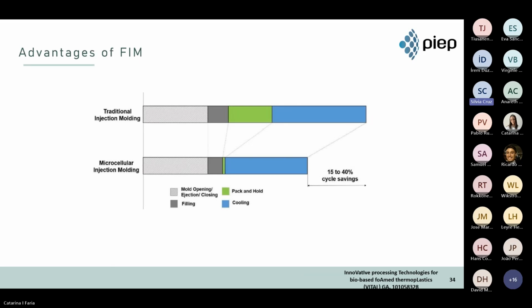So why use foam injection molding? The advantage of this technology compared to the conventional injection molding is, to start, the cycle time reduction. It could be reduced between 15 to 40%. Why? Because packing in the holding phase is given by the nucleation phase, and the cooling is also faster due to lower melt density and lower thermal conductivity.